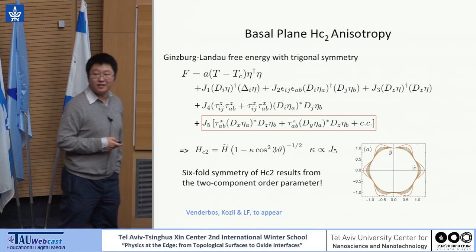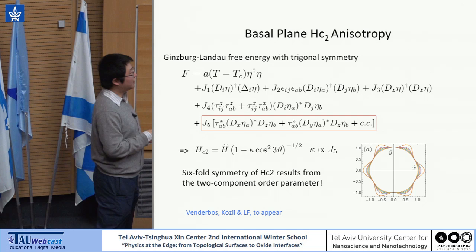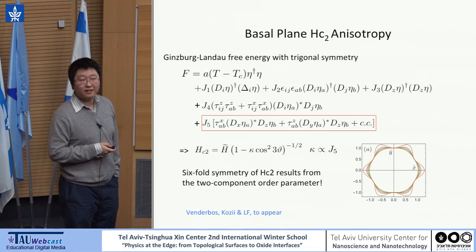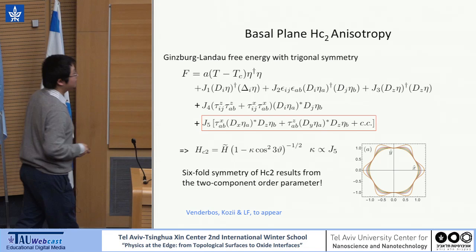So if we were dealing with an S-wave superconductor, even in the trigonal crystal, in Landau-Ginzburg theory, the upper critical field is actually fully rotationally invariant. So having this six-fold modulation is an evidence for the two-component order parameter.